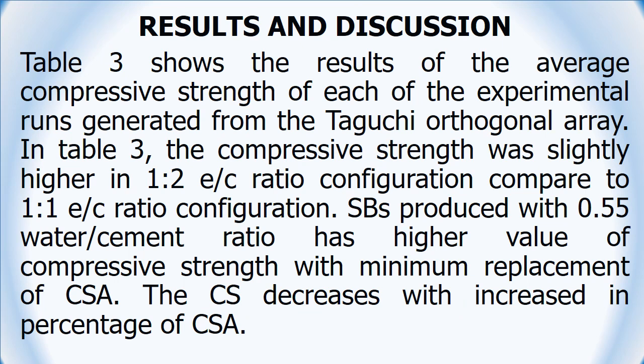Table 3 shows the results of the average compressive strength of each of the experimental runs generated from the Taguchi orthogonal array. The compressive strength was slightly higher in the 1:2 EC ratio configuration compared to the 1:1 EC ratio configuration. Sandcrete blocks produced with 0.55 water cement ratio have a higher value of compressive strength with minimum replacement of coconut shell ash. The compressive strength decreases with increase in percentage of coconut shell ash.